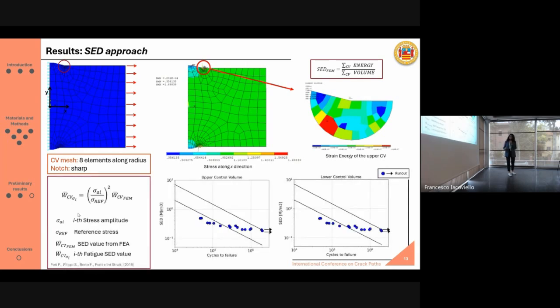Then, using this equation, which is quite famous in literature, we could compute the fatigue strain energy density values. So here we put the strain energy density coming from the finite element analysis. Here we have sigma ref, which is the 1 megapascal that we applied for the simulation. Sigma Ai is the stress amplitude for the fatigue test, and here we have then the SED values. Here we have the SED values plotted versus the number of cycles to failure for the upper and lower contour volume of our specimens. We can see how some of the data do not fall within the scatter band that is available in literature. Maybe this could be due to secondary effects that may be introduced during the fatigue test, as it is a tension compression test.